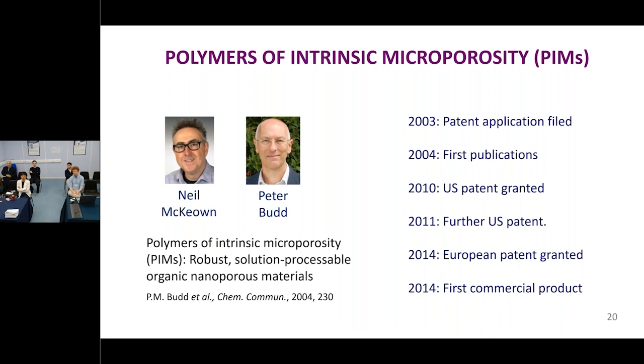Okay, so that provides the context and the background and some of the issues. And now I'm going to focus on my favorite polymers, the polymers of intrinsic microporosity, or PIMs. And the story of PIMs goes back to the early 2000s when Neil McKeown, who at that time was at Manchester University, and I were actually looking at trying to create networks which behave a bit like zeolites. And then along the way, we made something which was intended to be a model linear polymer to compare. And we realized we had a linear polymer which actually behaved in many respects like a zeolite or activated carbon. But it was processable.